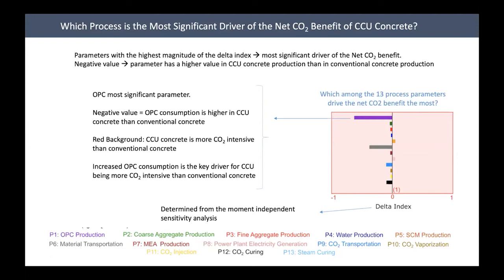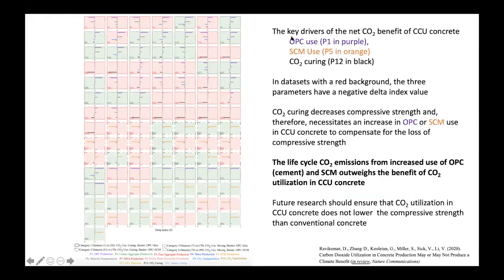So we ran this quantitative sensitivity analysis for each of the 99 data sets. And what we discovered validated what we saw in the scatter plot analysis. OPC consumption is a key driver. Supplementary cementitious materials are another key driver, and so is the amount of energy you use in CO2 curing. And out of the 99 data sets, in 51 data sets, using carbon dioxide to produce concrete actually increases climate burden. And the key reason for that is that when we use CO2 to produce concrete, it reduces the compressive strength of concrete.